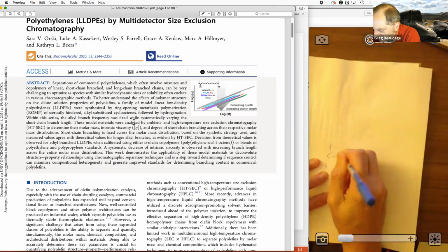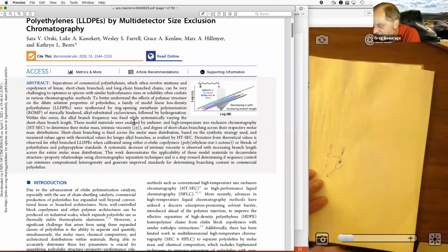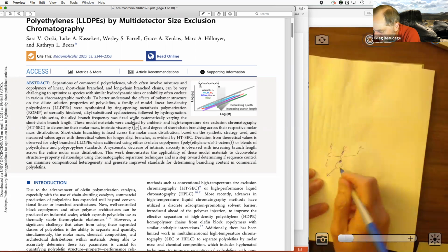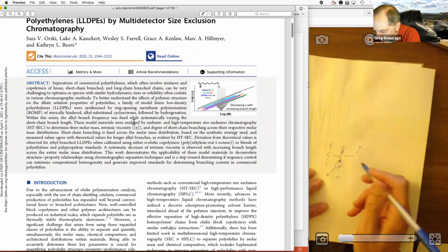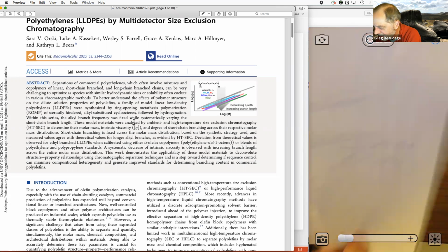Oops, these H's can get lifted off, and then you're left with a free radical on the carbon. Right? When you have a free radical, it can find a double bond, it can react with it. That'll make a long chain branch if you have polymers. So we're starting with a polymer that has double bonds.